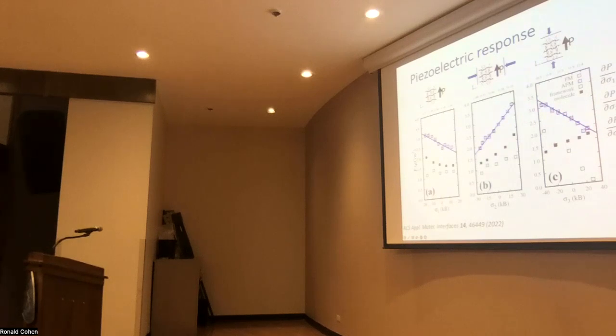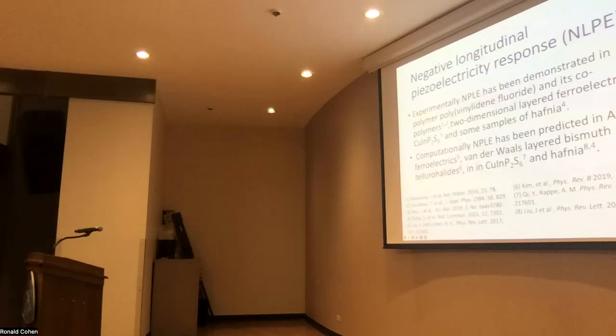quite a counterintuitive response. The subject of negative piezoelectric response has received quite a bit of attention in the literature at this point. Experimentally, there are just very few materials that have been demonstrated to have negative piezoelectricity. Among them are PVDF and its copolymers, two-dimensional layered ferroelectrics, as well as some samples of hafnia. Computationally, however, there have been quite a few predictions, including predictions in ABC ferroelectrics, van der Waals layered bismuth tellurohalides, as well as some hafnia predictions.